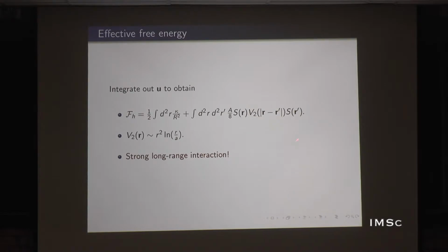No, because these coefficients scale with the shear moduli. The shear moduli are 0 for a lipid membrane, so this interaction disappears. A lipid membrane is just a fluid, a layer of fluid. A fluid doesn't have shear moduli, and you have no more solid. Exactly. This factor of A scales with the shear moduli.